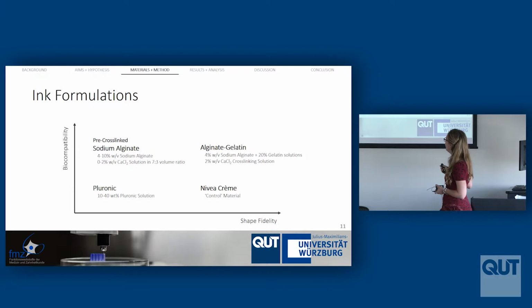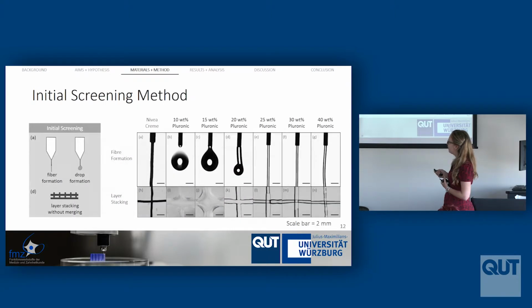And then I also used a blend of alginate and gelatin, so both natural polymers, and this gave me a hydrogel with very good shape fidelity, but that was also really biocompatible. And so this is being used all around the world for a lot of different applications because it's ticking all our boxes by the looks of it. So this was my first initial screening. I said we want to look for fiber formation and not droplets, and we want to make sure that we can stack it in nice pretty shapes for making our ear constructs or whatever we want.